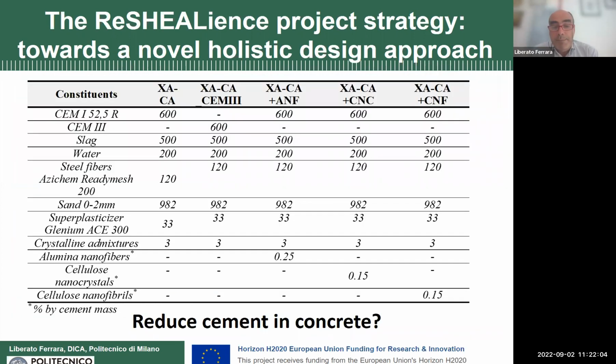So, I said one of the objectives is to reduce cement in concrete. And if you look at the mix design that we have employed, you see, oh my God, I have 600 kg per cubic meter of cement in my mix design, whereas for a regular concrete, I have 350 more or less. So am I really reducing cement in concrete? Well, if I look at the cubic meter as a unit, surely not.